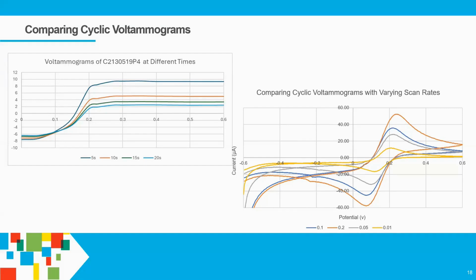So we had our P4, which here is just under 10 microamps, compared to a cyclic voltammogram. And the main thing to notice is only one of them really tells us roughly 10, but it's not very good. And also where it starts to level off, that is where our best potential for this mediator is. It's roughly about 0.29 volts, which doesn't equilibrate anywhere in the cyclic voltammograms. So we're telling the end user what voltage to use a mediator with this material.